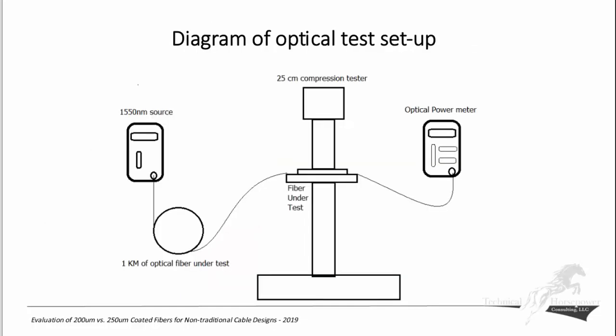Now, this is the actual schematic of the test setup. We used a kilometer of fiber ahead of that gauge length in order to eliminate any of the cladding effects that would have occurred from the source. So we were trying to be fairly fair about this and not look at a worst-case scenario. I believe that if you took the 1 kilometer out there and did that directly, you would see a lot of cladding effects as well. And then the compression tester just basically used these 2 platens and an optical power meter to read the delta of attenuation prior to, during, and after compression.